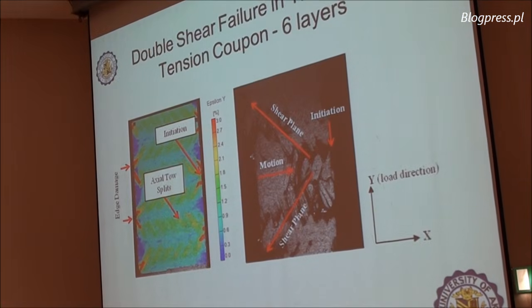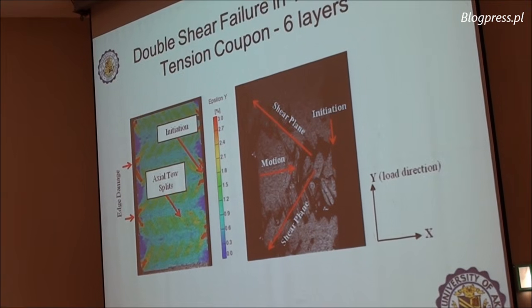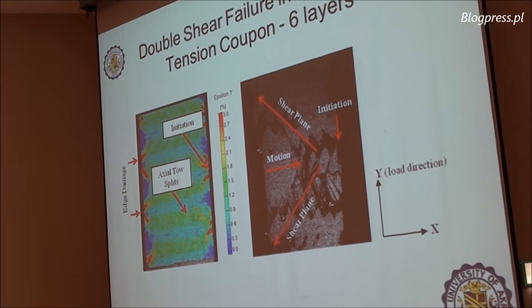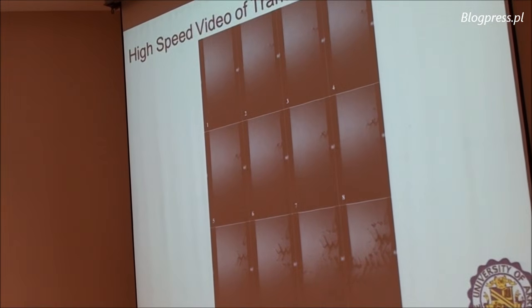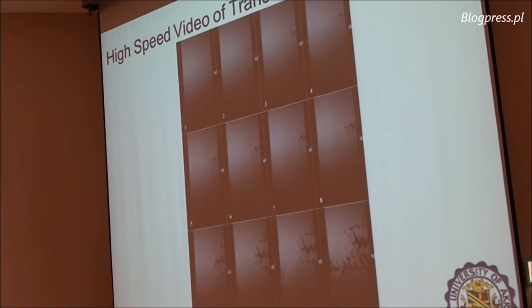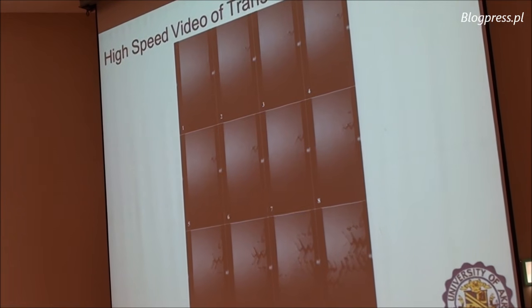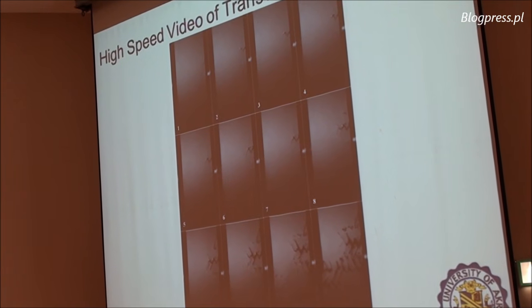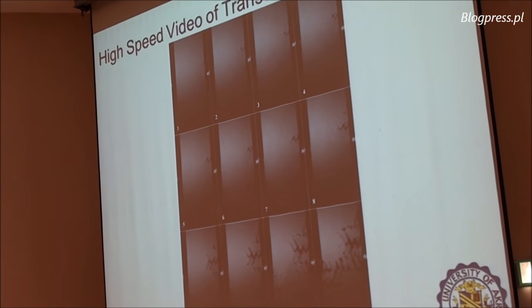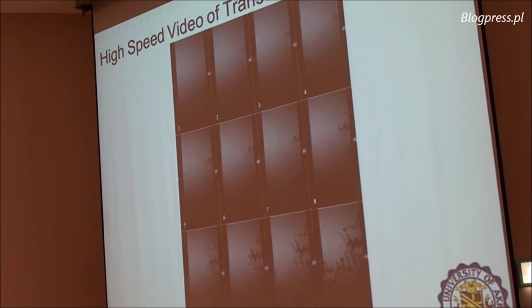And again, a lot of tests showing the mode of failure under tension, and these are pictures from the high-speed cameras that show how quickly, this is 40,000 frames per second, so within 12 frames of the 40,000 frames per second, you can see the damage progression. So you have to capture that very quickly, otherwise you don't see that at all.